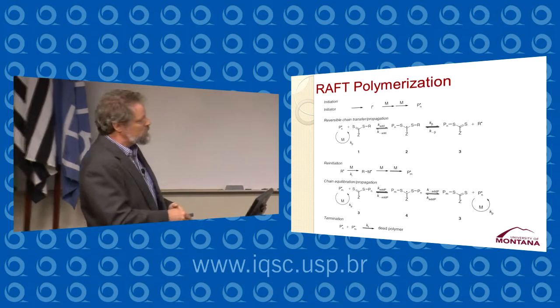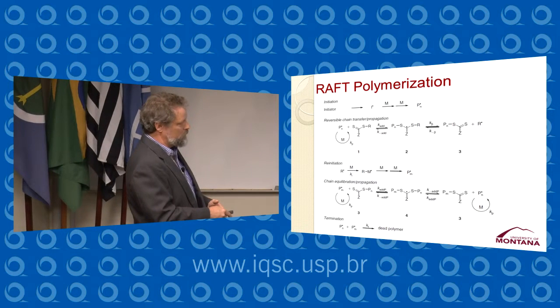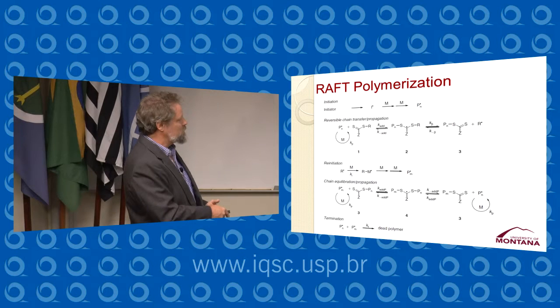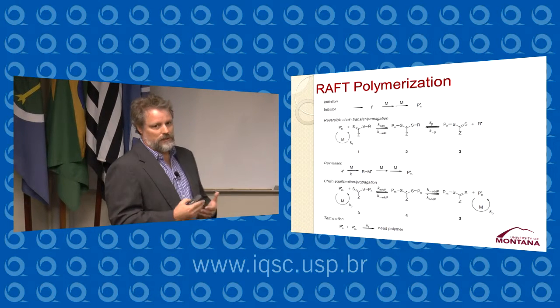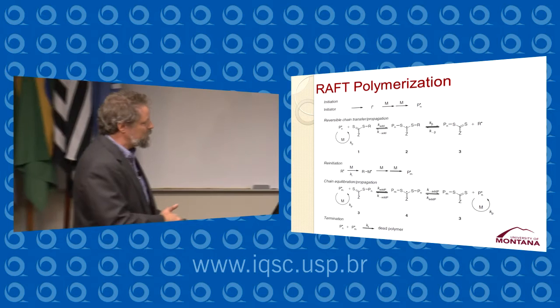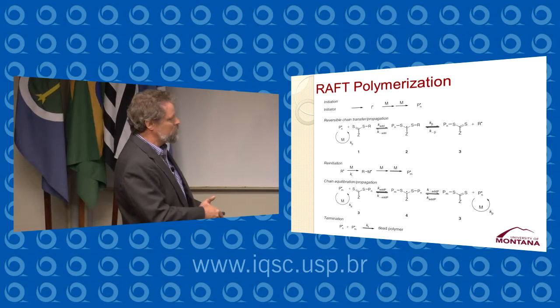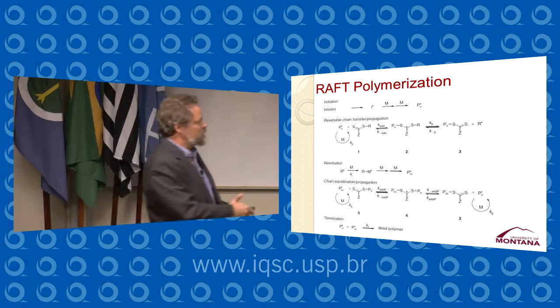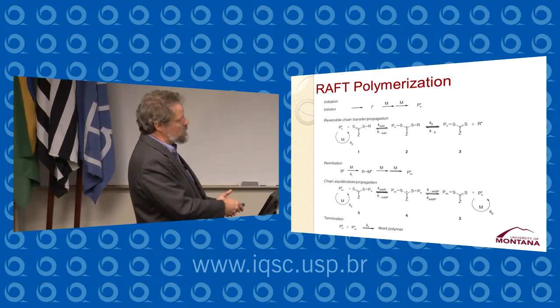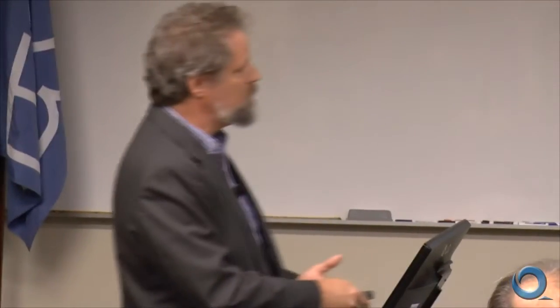And because the concentrations of these free radical growing chains is quite low, the chances of seeing this sort of a termination reaction are quite low as well. So we don't expect to see very much dead polymer formed by this mechanism. When we stop the reaction, we expect to have mostly this structure of polymer with the chain transfer agent attached to the end of the growing chain. It's still a living polymer at that point. We can stop a polymerization, we can purify this material, and then we can start a second polymerization using this material as our chain transfer agent.